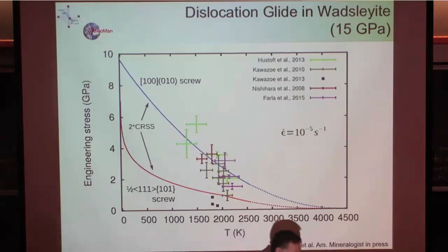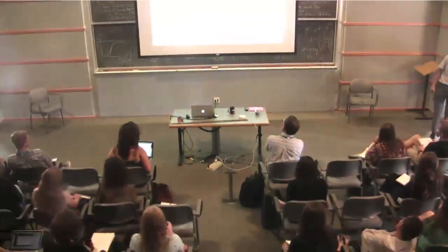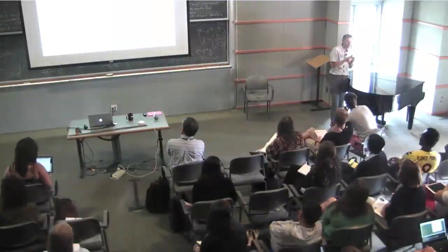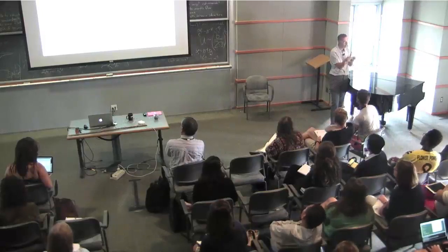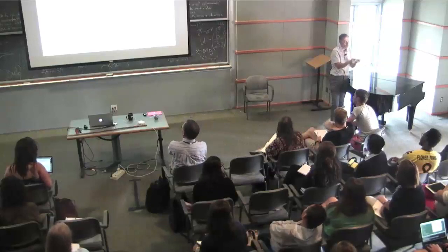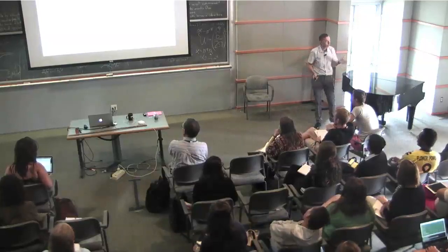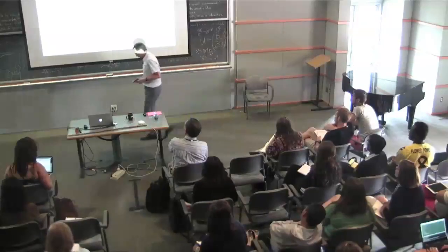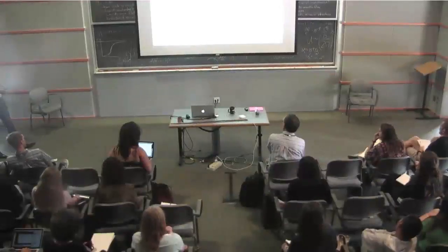When we see kinks in the red and blue curves, are those caused by phase transitions? Oh, you know, here. That doesn't look like exponents. No, it's because when you have a dissociated dislocation, I described the kink pair mechanism. It's easy for a single line. When you have split it into two lines, then you have to describe a more complex kink pair mechanism. There are two mechanisms. One possibility is that you nucleate simultaneously a kink on both dislocations. The other possibility is that you make one and then the next one. And the two mechanisms do operate depending on the stress, and this is the difference between those two regimes. Well, we have to deal with that, but at the end, it doesn't make a huge difference, but this is what's hidden behind. I could not go into all those descriptions.